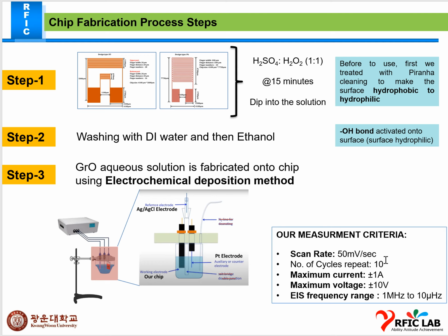So this is the chip fabrication process step. I just have to skip one, but before that, I want to share my measurement criteria. The scan rate of this machine is 50 millivolts per second. The number of cycles repeated is 10, but this week I have to use 15 cycles because of the thicker deposition of the graphene. Last time we used 10 cycles and the thickness may not be suitable for our chip, so we need more thickness, and that's why I want to exceed the cycle. So this week I use 15 cycles on each chip, and the maximum current is 1 ampere, the voltage is not more than 10 volts, and the EIS frequency is 1 megahertz to 10 microhertz.